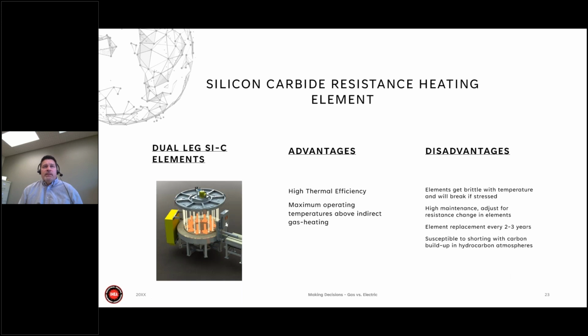The silicon carbide resistance heating elements. This one here is a dual leg silicon carbide heating element where it's installed at the top of the furnace of this rotary hearth furnace. And you can see there the light yellow lines are the glow bars that are extending into the furnace around the inner diameter of the furnace that has been removed to show the inside. These silicon carbide elements have high thermal efficiency, and they have maximum operating temperatures that go above indirect gas heating, so you can apply them to higher temperature processes.